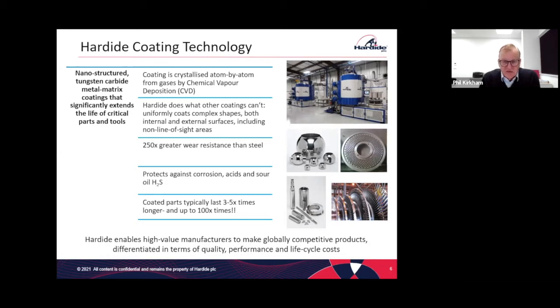So the process is such that the components are placed in the chamber, heated up to around 500 centigrade. A mixture of 4 gases is introduced into the chamber, and these gases react together on the surface of the component. And as I said previously, the coating is actually crystallized atom by atom over the whole surface of the component that we want to coat. We can, of course, mask certain areas of the component where the coating is not needed or not wanted. But this coating grows atom by atom. The layer builds up to a thickness of around 50 microns, which is around 2/1000ths of an inch, or roughly the thickness of a human hair. So that's the thickness of the working coating.